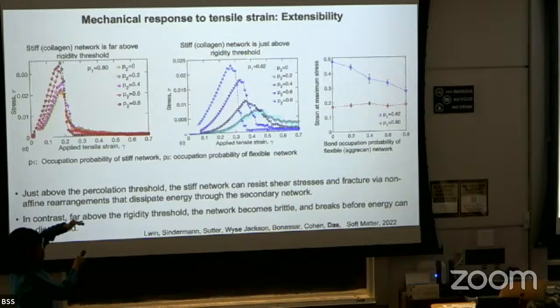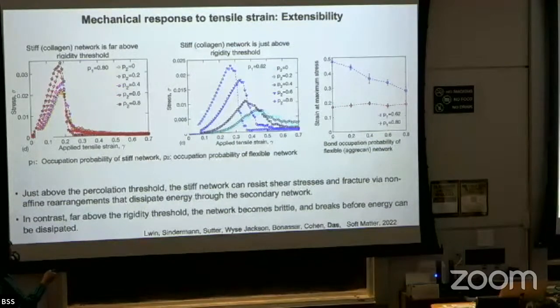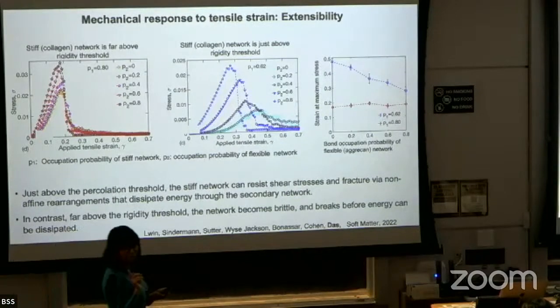But when the collagen network is just above the rigidity threshold, so still rigid but quite sparse, you can see that as you change the amount of aggrecan, two things shift. The maximum amount of stress that the network can bear, which is known as the peak stress, changes, and the more aggrecan you add, the more peak stress you will have. However, the strain at which you reach the maximum stress, which is a measure of the extensibility of the material, so the strain at which the material will start breaking and fracturing, actually decreases as you add more and more material. So why is this? This is a very important point.